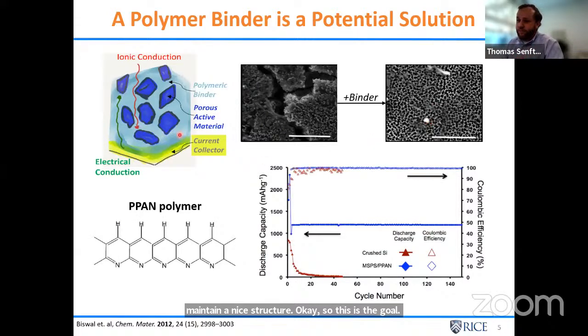We want to understand what properties of the polymer, in this case, pyrolyzed polyacrylonitrile, are responsible for effectively maintaining the structure of the electrode. And what the Biswal group showed, effectively, if you compare the performance of the electrode over several cycles of the polymer binder composite to just the pure silicon, clearly the pure silicon fails rapidly, but the binder is quite stable. So what does this interface look like?